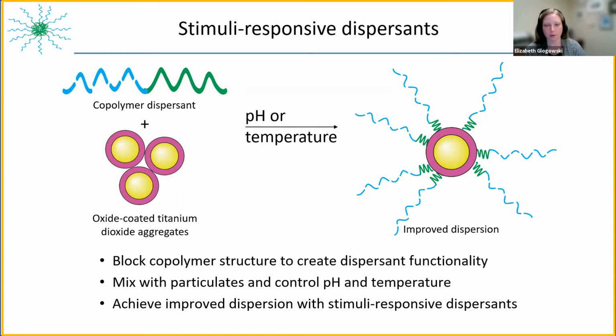We've been working with stimuli responsive polymers, and we're looking at these as polymer dispersants, as I said, for the titanium dioxide. Now, titanium dioxide particulates are not used directly or in their raw form, because the titanium dioxide can actually degrade organic components over time. And so they're all coated with different potential coatings. The most common one is an aluminum oxide based coating. And sometimes they mix in silicon dioxide and zirconium oxides. And so that changes the surface chemistry of the titanium dioxide particulates. And so the dispersant that's used needs to be adaptable for those coatings as well.